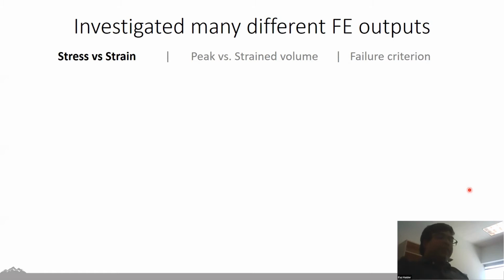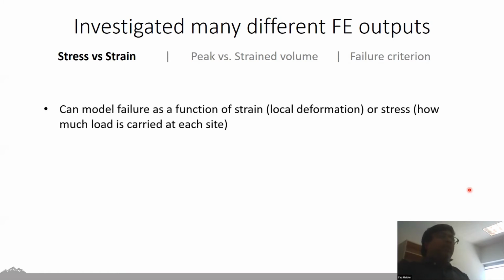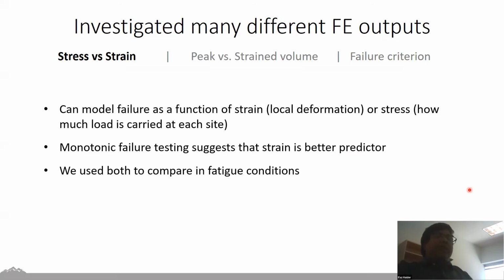So first, let's talk about stress versus strain. Essentially, we can always model failure either as a function of the strain, which is the local deformation that the bone is experiencing, or stress, which is basically how much load is carried at each site. Both are sensible, but material science and material level testing suggests that strain-based measures are probably more robust, because the strength of bone changes a lot with its density, and yet regardless of density, bone has a tendency to fail at a very similar strain. And so we used both conditions, and we wanted to see which one would work better in fatigue.